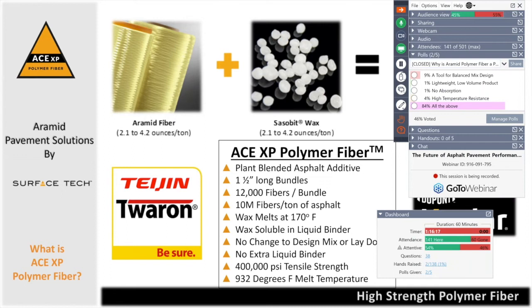It's an inch and a half long bundle. Those bundles are 12,000 fibers coated with wax. So that gives you about 10 million of those individual fibers per ton of asphalt. And as you can see below, that's 400,000 PSI tensile strength of those fibers. So you're putting a lot of tensile strength into a product, asphalt, that tends to not have a lot of tensile strength. And it goes in a three-dimensional manner.